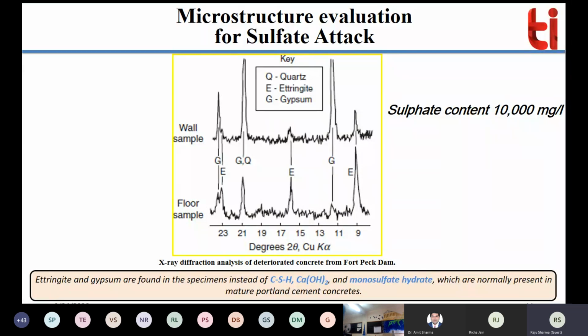So they wanted to find out the reason behind that. They took a sample from that particular wall; a sample of, let us say, 15 or 20 grams is sufficient. They just collected the powder sample from there and tested it by XRD. They also did tests to find out the sulfate content in the water, and they found 10,000 milligram per liter, which is in the range of severe sulfate.